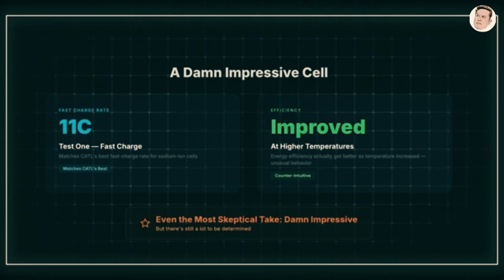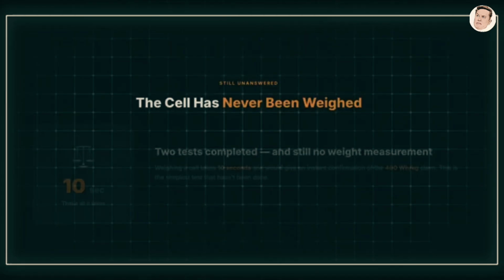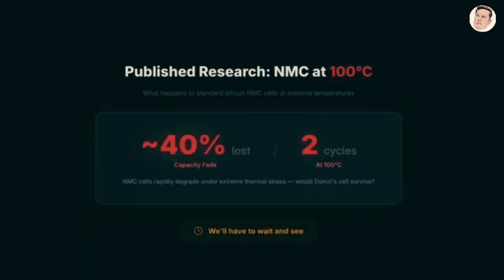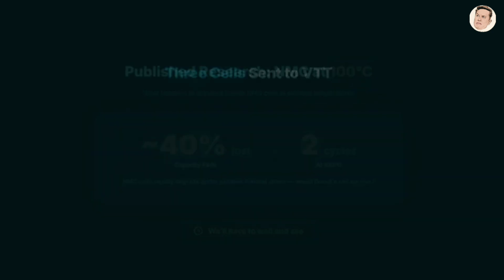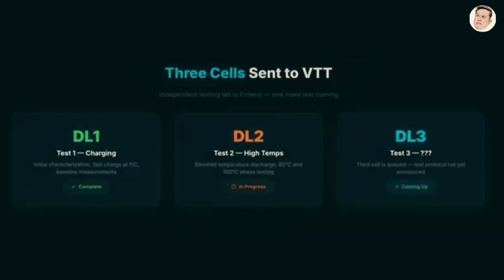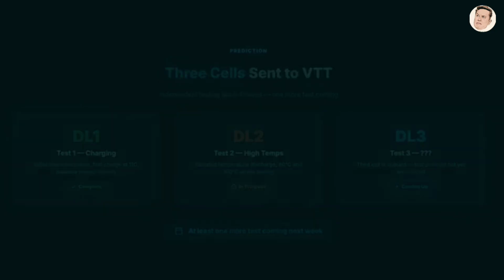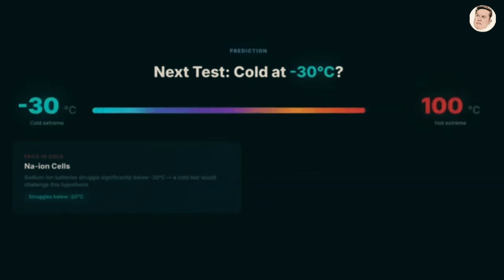Now, if you're thinking any battery delivers more capacity when it's hot because there's lower internal resistance and ions move faster, that's basic Arrhenius kinetics. You're right. That's not special in and of itself. So, we tried to find a single commercial NMC battery cell from Samsung, LG, CATL, really anyone with published discharge rates over 80 degrees Celsius. And we couldn't find a single one because, well, they don't test in that kind of regime.